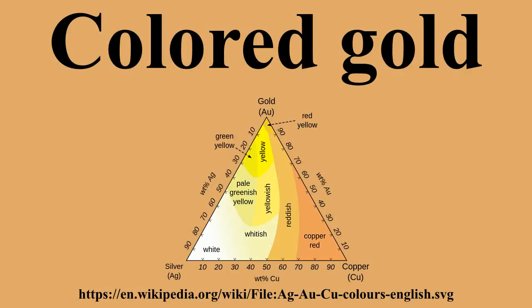Blue gold. Oxide layers can also be used to obtain blue gold from an alloy of 75% gold, 24.4% iron, and 0.6% nickel. The layer forms on heat treatment in air between 450 to 600 degrees Celsius. A rich sapphire blue-colored gold of 20 to 23 K can also be obtained by alloying with ruthenium, rhodium and 3 other elements and heat treating at 1800 degrees Celsius to form the 3 to 6 micrometers thick colored surface oxide layer.